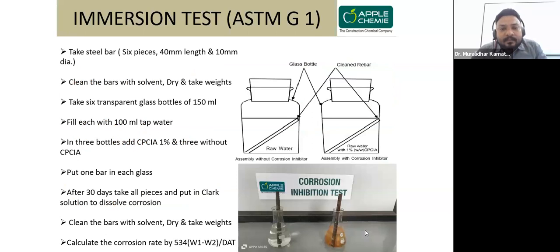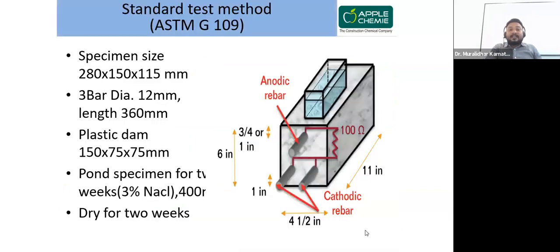So we can't increase above that. Again, this is the immersion test, you can see it in the picture, and we are going to check three bottles: three with CPCIA 1%, that is the corrosion inhibitor solution, and three without CPCIA. Then we calculate the weights W1 and W2 by difference. These are the specifications. This is ASTM G109, which requires a year-long test, and only after a year can we conclude this.